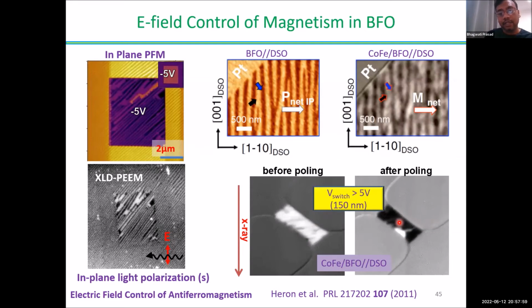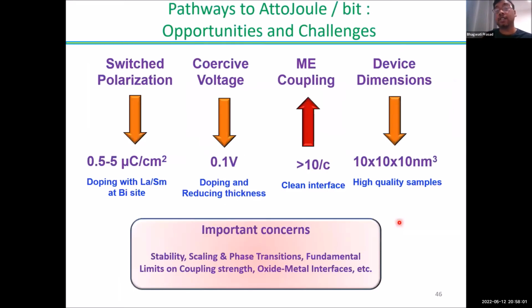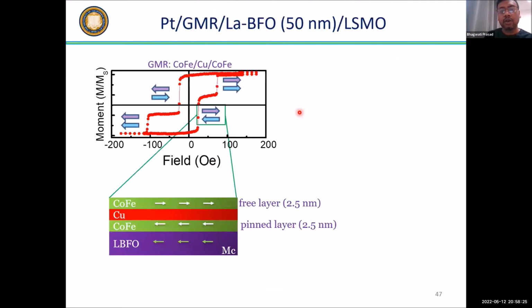So with the thick films, the purpose is how to reduce the energy. You want to get the switching at lower voltage, and for that we have to do some engineering. We need to reduce the switched polarization, reduce the coercive field, and at the same time make sure we have enough magnetoelectric coupling. We also want to make small devices. When you do that, there are a lot of concerns one has to take care of. So we have done that.